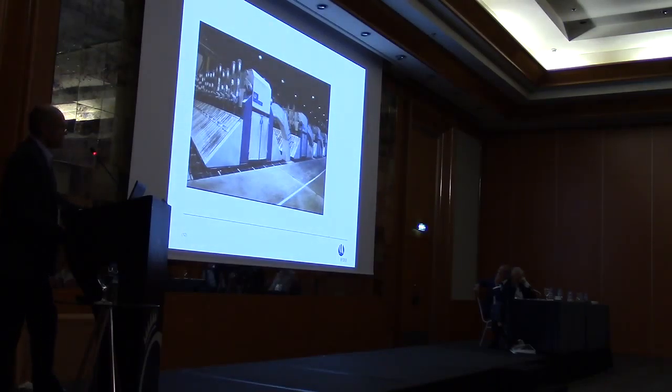So moving into the aluminium technology world, this shows an aluminium electrolysis cell. One cell of this technology version produces about 1,200 tons per year, and there are roughly 350 cells in a full-scale profile. One cell is 4.5 times 16 meters, and the full pot line is about 1,200 meters long.